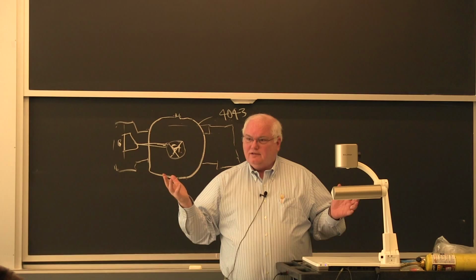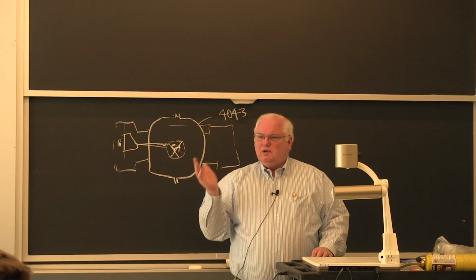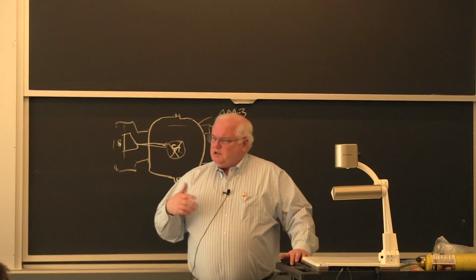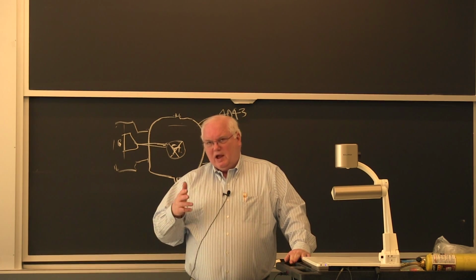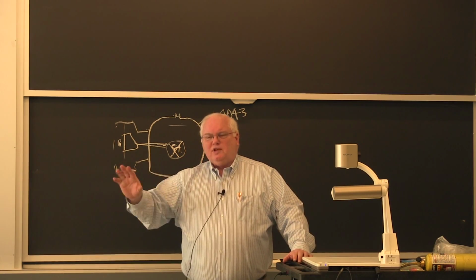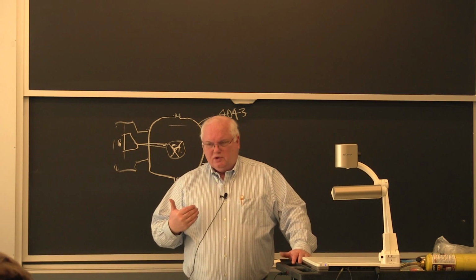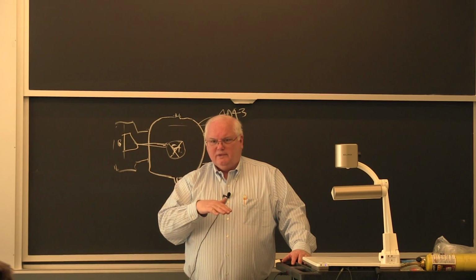It's a little calorimeter, right? And we showed that if you didn't have any layer, you didn't absorb any energy, because aluminum's a great reflector. But with an anodized layer, and I don't remember, I'd have to go back and look at the patent, somewhere between 6 and 10 microns was sort of the best. I actually calculated that from the wavelength of the light. It makes sense in terms of the wavelength of the laser: you want it thick enough to have good absorption and thin enough that you're getting the high conductivity aluminum close to the surface, right?